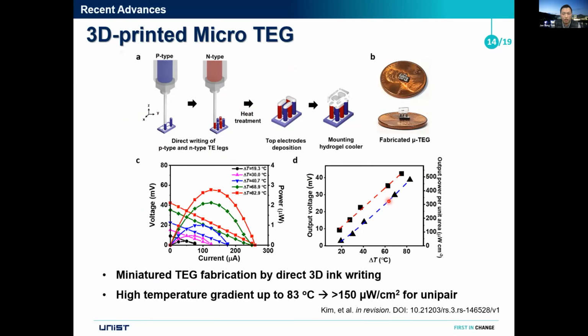And then we have fabricated a micro thermoelectric generator by direct 3D printing. You can see the size of this module is about 2 millimeters, and you can see quite a reliable power performance depending on the delta T. One should note that the delta T created across this thermoelectric leg is more than 80 degrees Celsius, which is quite a rare case in micro thermoelectric modules because they are typically fabricated by MEMS technology. So high aspect ratio thermoelectric legs are impossible in this process.